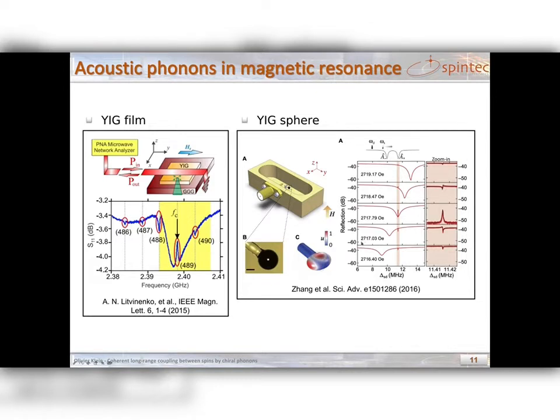This is actually an interesting experiment done this time on a YIG sphere, where the acoustic mode is a deformation mode of the sphere. In the spectroscopy, when you increase the magnetic field, you see a broad peak that shifts in position in frequency according to the gyromagnetic ratio. But what you can see is that there is a sharp feature always located at the same frequency position, and this sharp feature should be associated to an acoustic resonance. And you can see that this sharp feature can either be a peak or a dip, depending on the position, or it could have this dispersion shape, as you can see here, which is also called a Fano resonance.